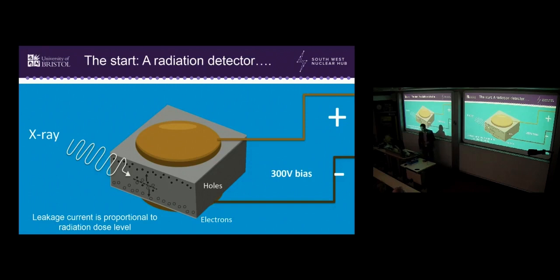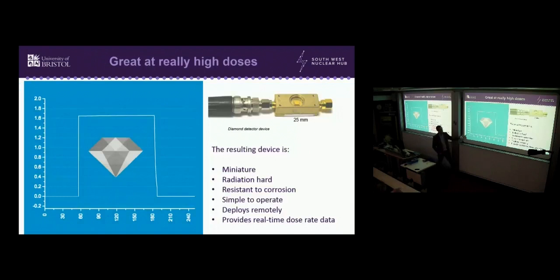And what that means is when you expose your diamond to a high flux of radiation, you get a current which is proportional to the dose which it's receiving. And the great thing about it is it's about the size of my thumb. It can go on a 150-meter armoured cable, so you can feed it in through the pipework into a facility. It's diamond, so it basically doesn't corrode. And you use noble metals as well, so they don't corrode either.